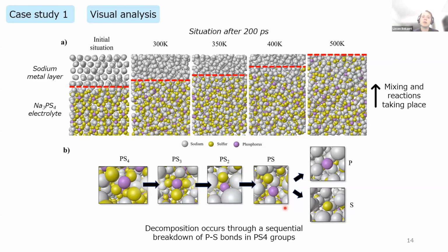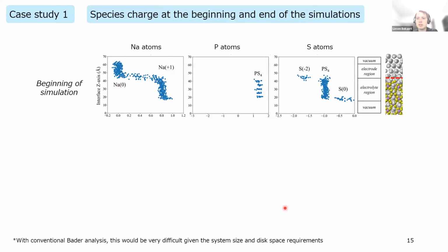It's really interesting to be able to analyze the charge and how it changes during these simulations. And here, Matlantis really provides a very important way of doing this, because what you would conventionally do is you would use, for example, Bader charge analysis. So Bader charge analysis, if you run it on a small system, it already produces many large output files, so you're limited with your resources. And especially with more than 1,000 atoms, that is very difficult to achieve. But with Matlantis, we can obtain this in just a few seconds, so it's really fast.